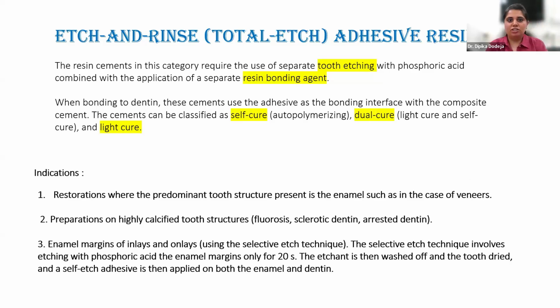So, okay, the etch and rinse, the total etch adhesive system. So as I said, it requires separate etching. They require separate application of the bonding resin and then your cement. Okay. So this could be self-cure, dual cure, or light cure. Where do we use, what are the indications for these type of cements? Where you have more enamel present, that is in case of veneers, where you have highly calcified dentine, like in cases of sclerotic dentine in your class 5s, your non-carious lesions, and in fluorotic dentine.